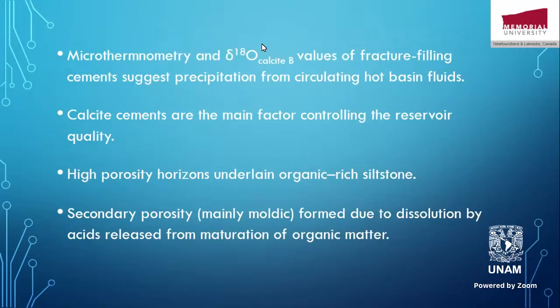The microthermometry and the delta O18 of the calcite values of the fracture filling cement suggest precipitation from circulating hot basin fluids. The calcite cements are the main factor controlling that reservoir quality, and the higher porosity horizons were found, in fact, attached or close to the organic rich siltstone layers, which means that part of these pores was caused by the organic acids produced from the thermal cracking of that organic matter, which dissolved the calcite that filled in between the grains. And the second type of porosity, as I said, is mainly moldic, formed due to dissolution by acids, as I explained a moment ago.